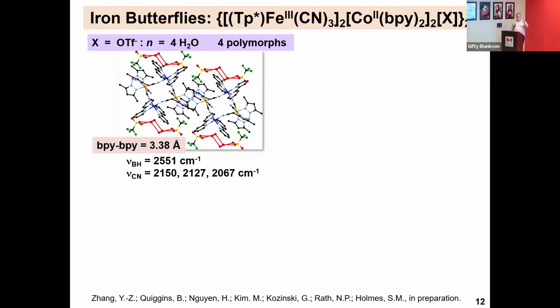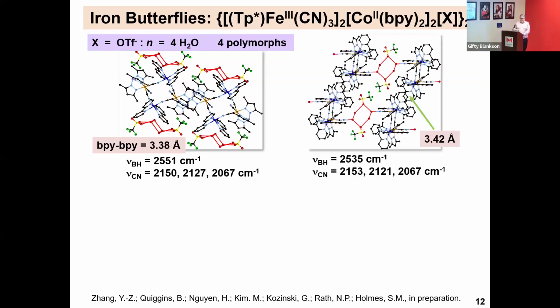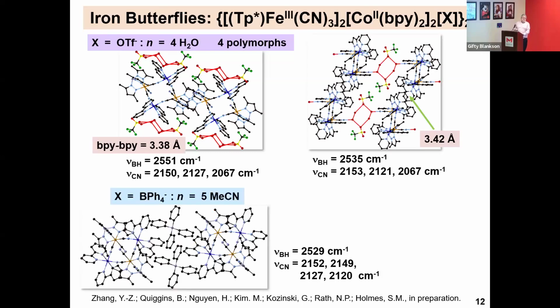Likewise, you get different chemical properties with regards to this project. These compounds all crystallize nicely. You can see these red lines are hydrogen bonding between red spheres. Those are lattice water. And triflate anions, trifluoromethane sulfonate, where the water molecules hydrogen bond to the oxygen atoms, that sulfate derivative, if you want to call it. Here's another one where you have hydrogen bonding between cyanides, lattice water, and triflates.